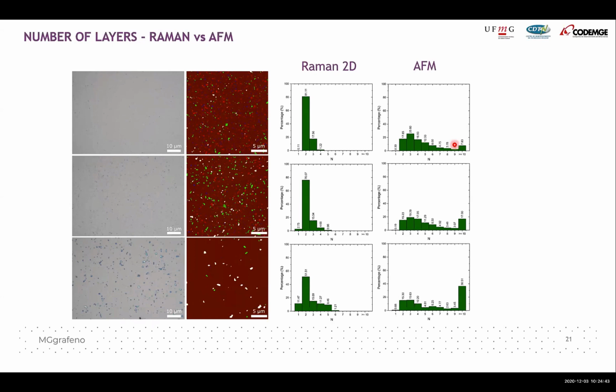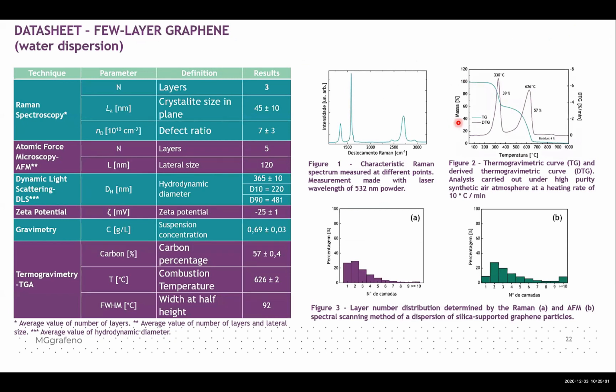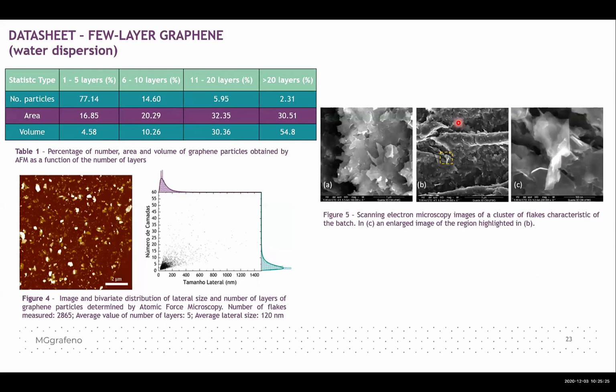So what does this mean? This means this is a material with 4 or 5 layers, but in this material, the electronic coupling between the layers is on average of 2 layers. So this is the kind of thing that has to be put in the data sheet. And what we have to do is to make all this very transparent. The customer has to know all the information, how the information was obtained, and what it means for the customer, for his application, and what it means for the batch-to-batch reproducibility. So we have really a very strong characterization framework, besides a very good production process and separation process, everything together.